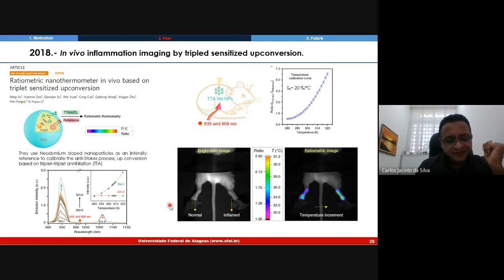The bright field image shows arthritis in the right leg of mice stimulated with carrageenan, while the left leg has the normal temperature, a normal control with no arthritis in this case. The ratiometric image revealed the luminescence and evaluated the temperature distribution in the two legs, indicating the presence of rheumatoid arthritis.